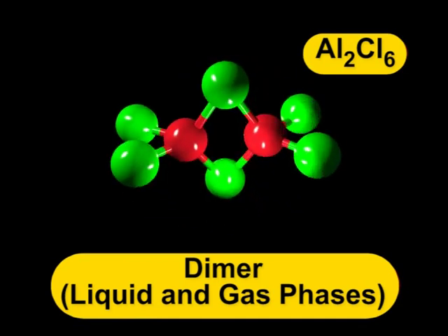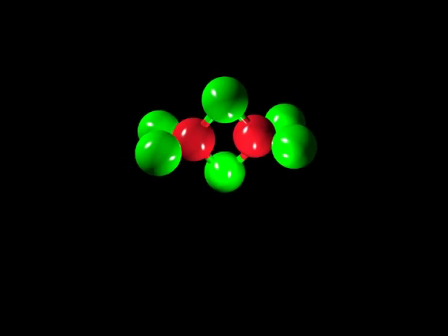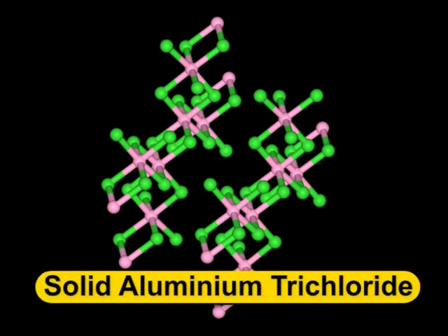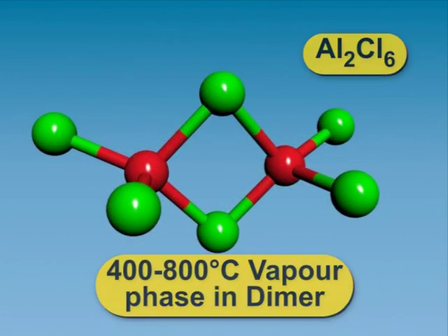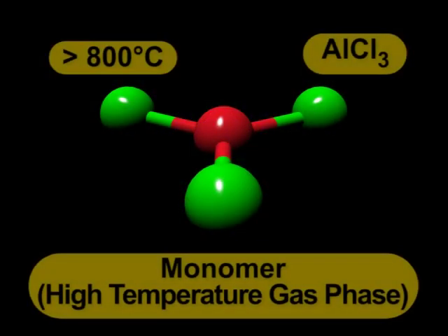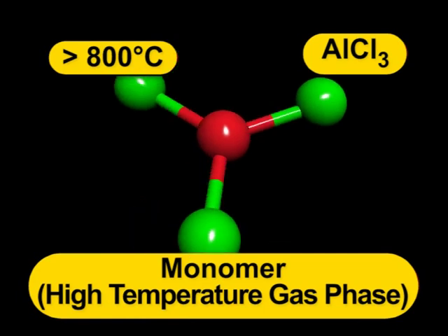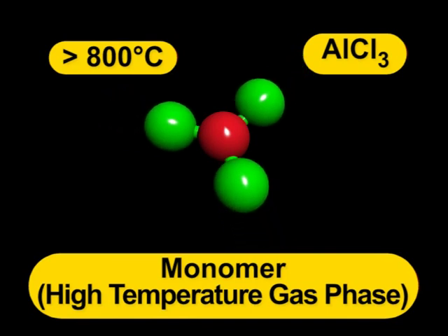In the liquid phase, it exists as the dimer Al2Cl6 with tetracoordinate aluminum. This change in structure is related to the lower density of the liquid phase, 1.78 grams per cubic centimeter, versus solid aluminum trichloride, 2.48 grams per cubic centimeter. Al2Cl6 dimers are also found in the vapor phase. At higher temperatures, the Al2Cl6 dimers dissociate into trigonal planar AlCl3 which is structurally analogous to BF3.